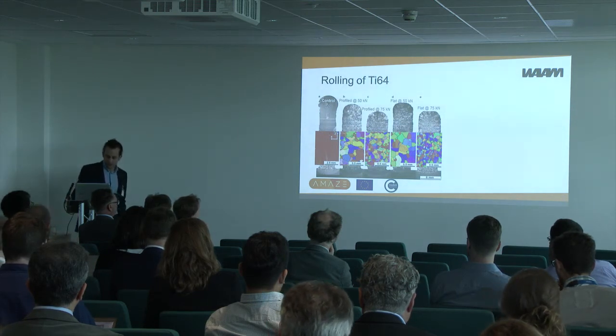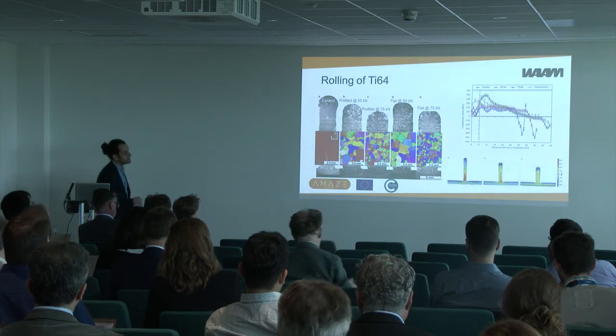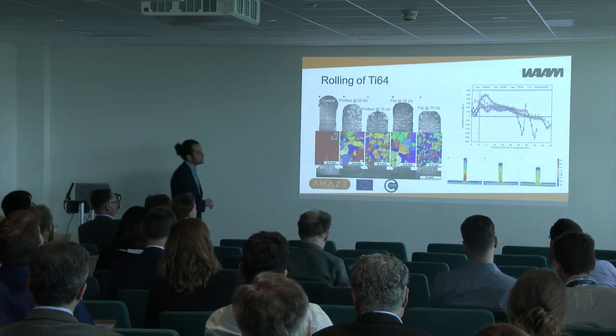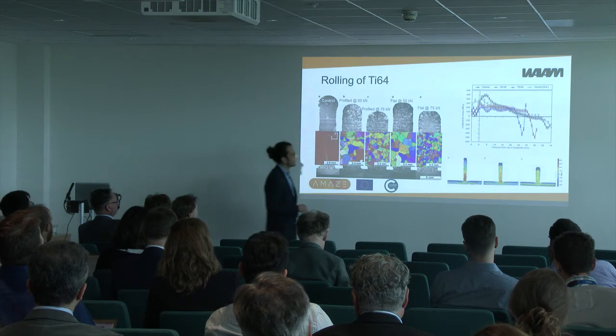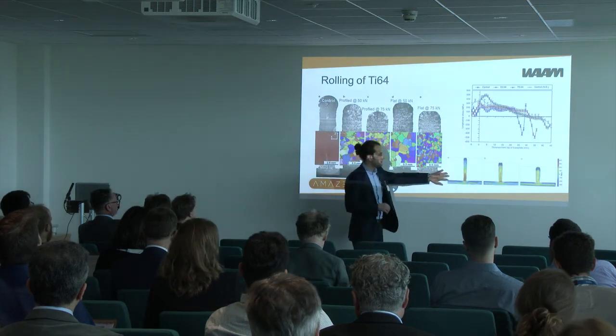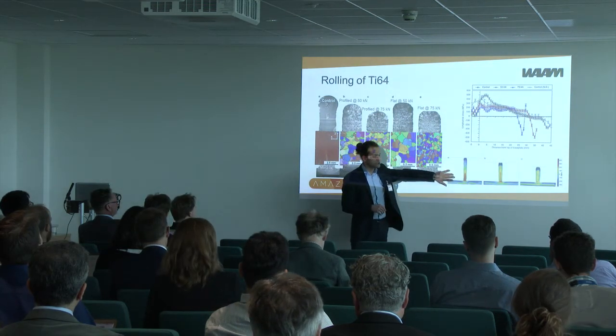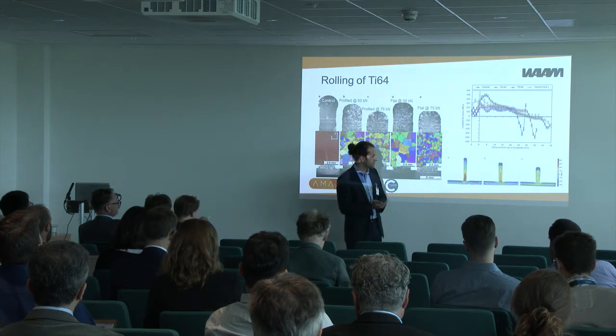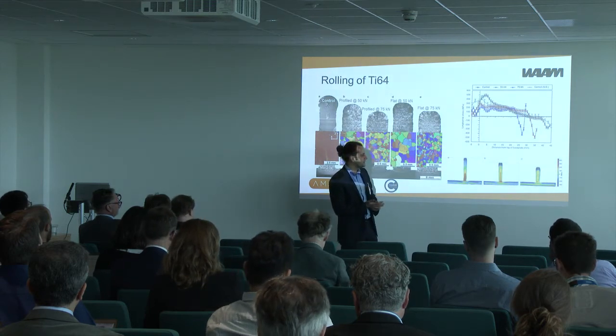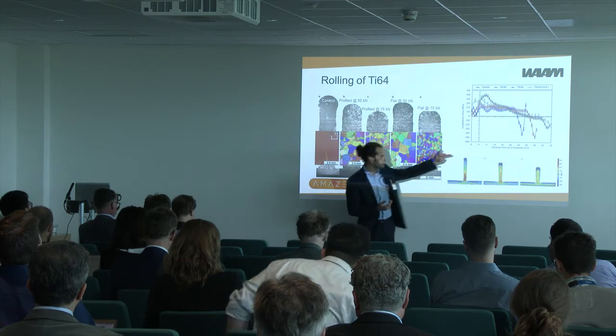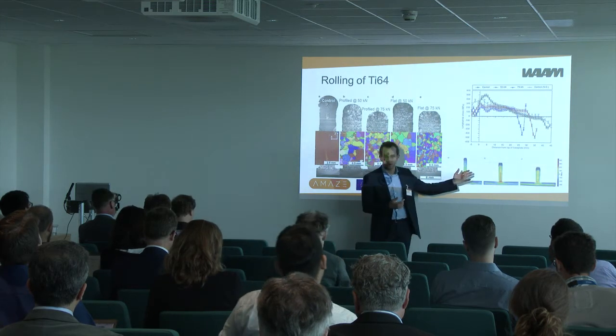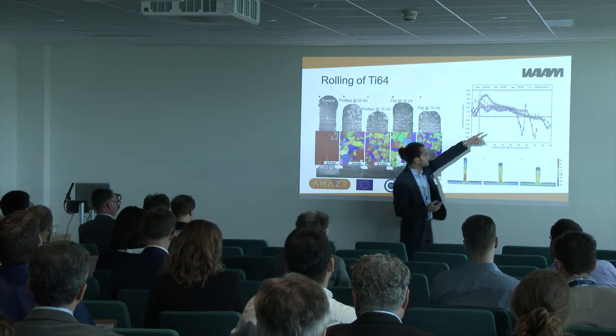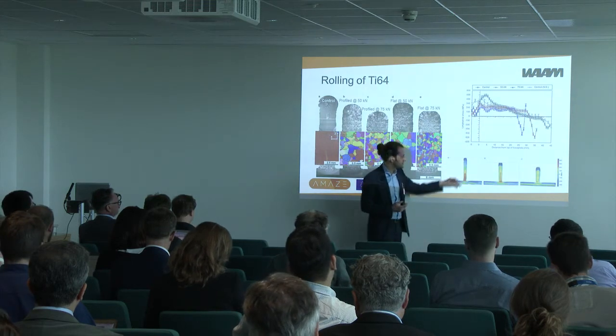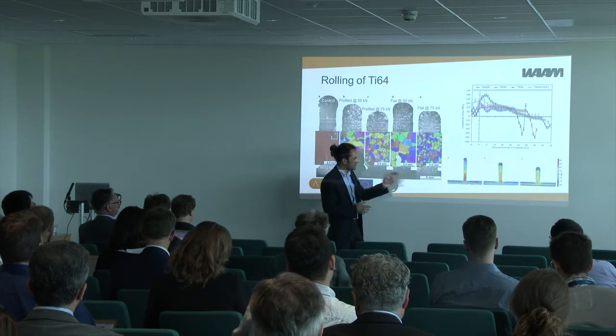We also measure the residual stress, and you can see here stress is measured with two different techniques. In this case, we are using a technique called contour method, and I have to thank the chaps at Manchester University for doing the measurements for us. It's a destructive technique, but it gives you a contour map of the stresses throughout the cross-section. While diffraction methods like those ones will give you just points, with the contour we can have a look also at the thickness.